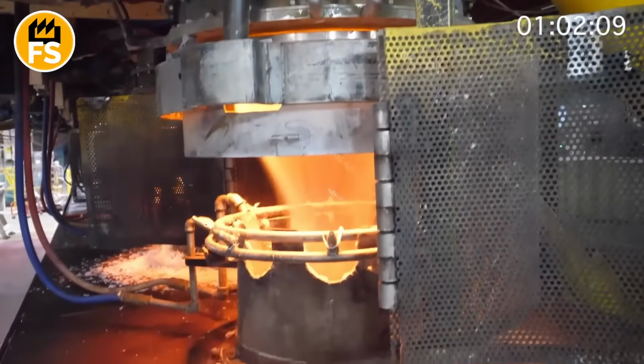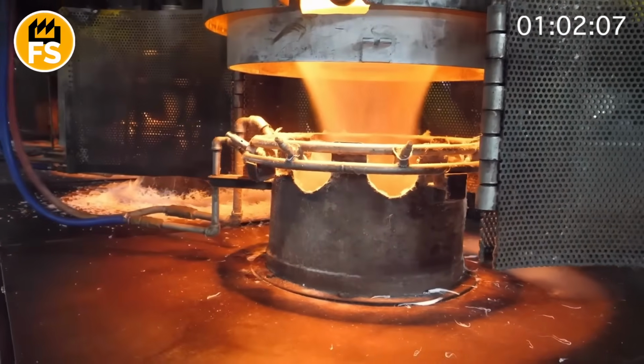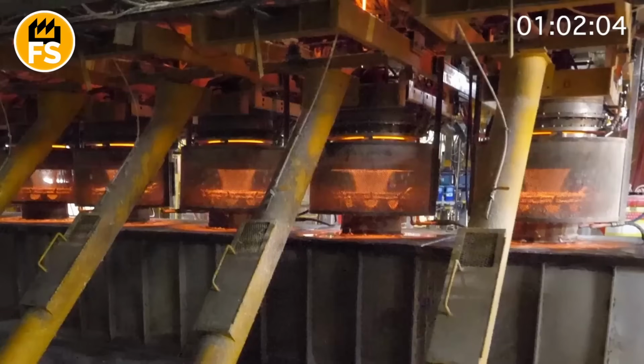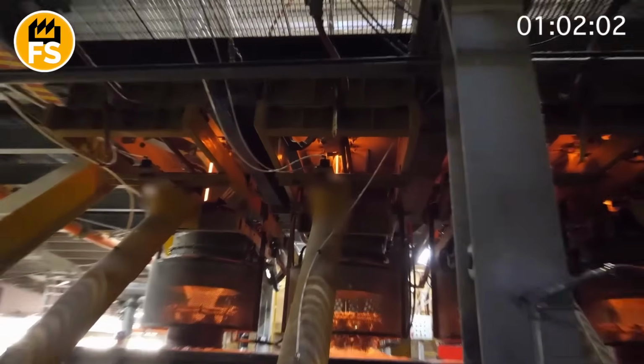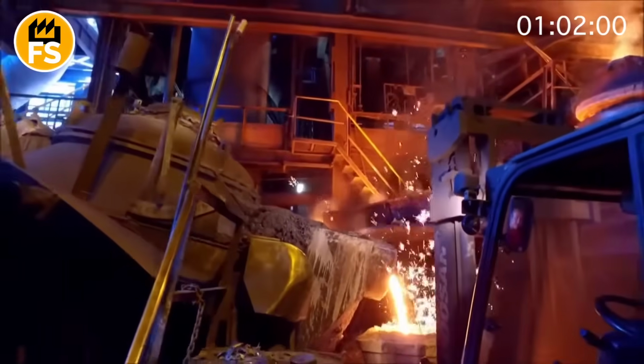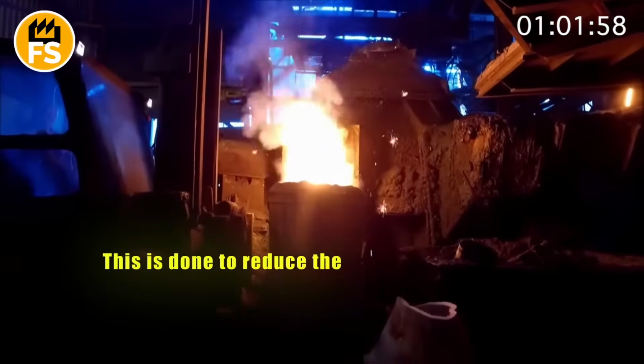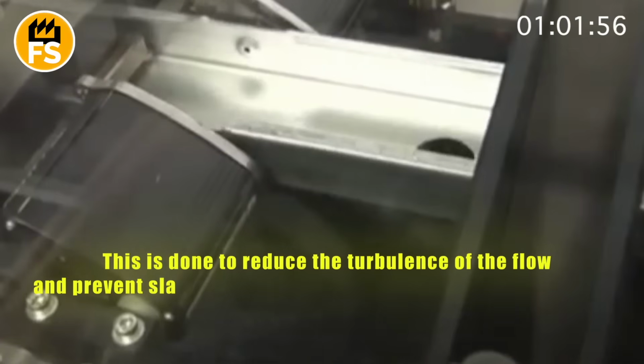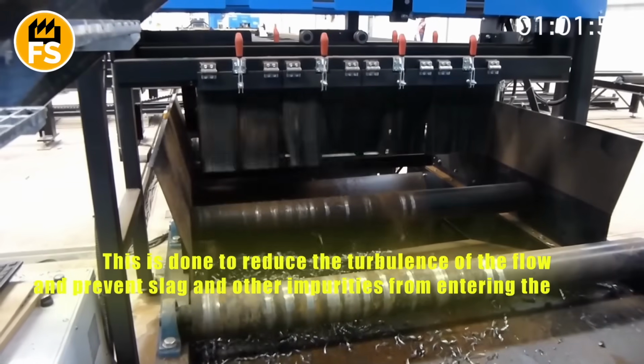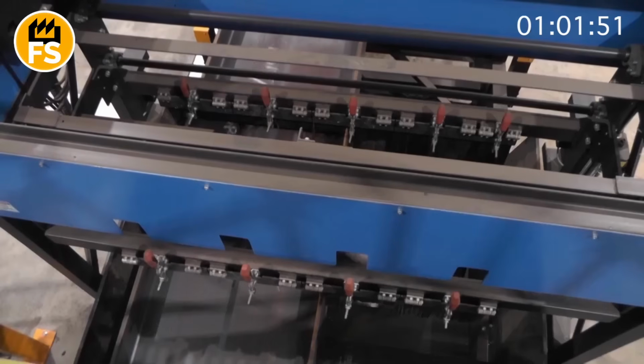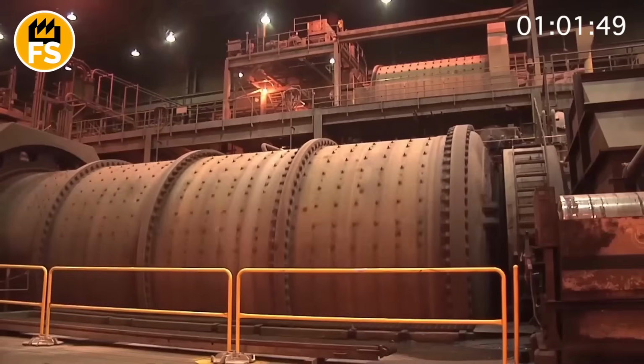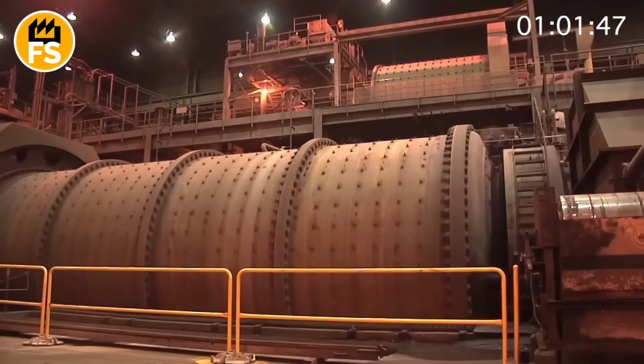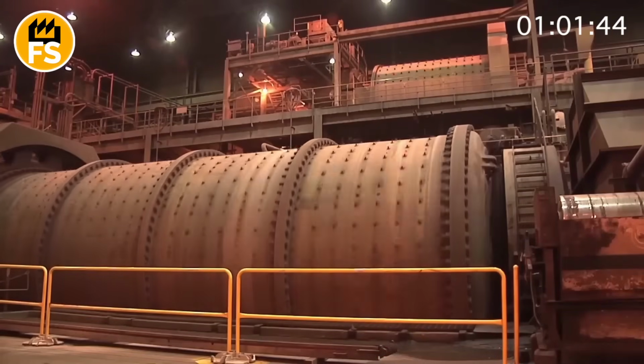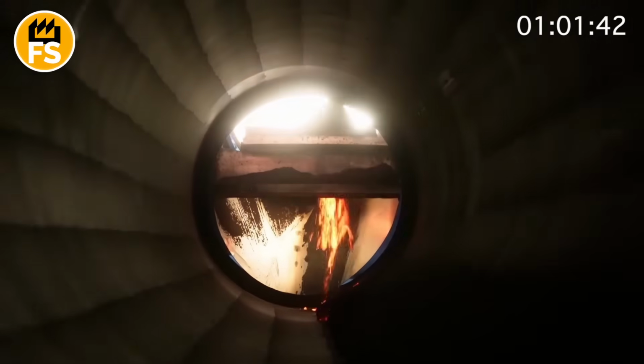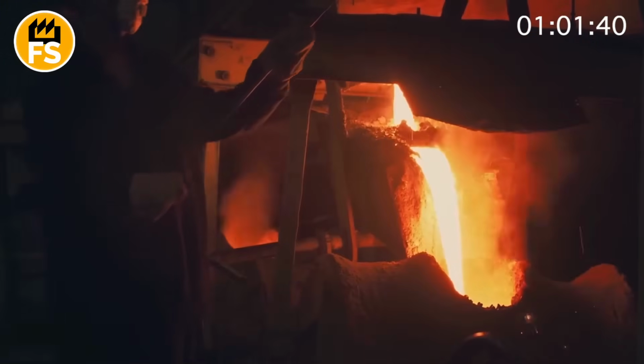From here, the stage of shape creation begins. The ladle is moved over a row of cylindrical graphite molds. A bottom pouring method is used. The metal is fed into the molds from below through a system of channels. This is done to reduce the turbulence of the flow and prevent slag and other impurities from entering the casting, ensuring maximum purity of the future wheel. For about 20 minutes, the steel solidifies, and the hot, still red cylindrical blocks, called blanks, are extracted from the molds. This is just a rough hint of the future wheel.